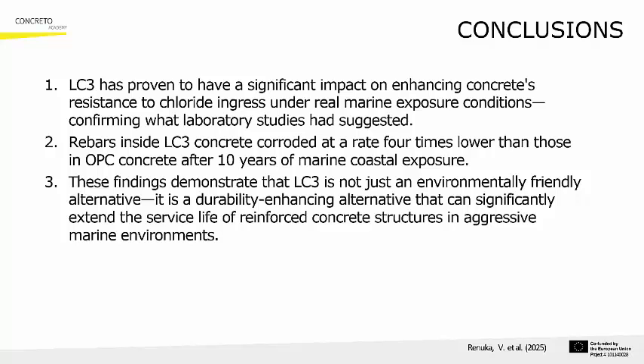The key conclusions derived from this decade-long study are the following. LC3 has proven to have a significant impact on enhancing concrete resistance to chloride ingress under real marine exposure conditions, confirming what laboratory studies had suggested. Rebars inside LC3 concrete corroded at a rate 4 times lower than those in OPC concrete after 10 years of marine coastal exposure.